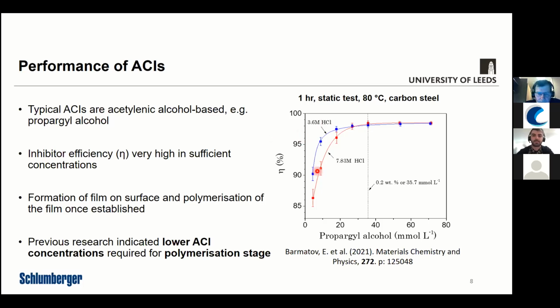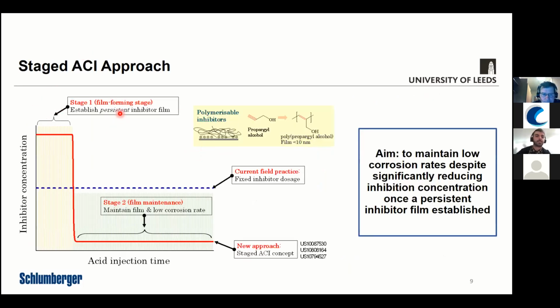But what Schlumberger had learned was that they can maintain this efficiency by reducing the corrosion inhibitor concentration once the film has been formed. So it raises the question, how effective could that be? Can you significantly reduce the concentration and maintain a protective film once the film is formed, based on how the inhibitor adsorbs to the surface and how it will polymerize, on that mechanism of inhibition? So the staged approach is essentially a two-stage process where during the film forming stage, stage one, the inhibitor will be added in high concentrations, allowing the persistent film to be formed. The inhibitor concentration would then be dropped, and that would maintain the film.